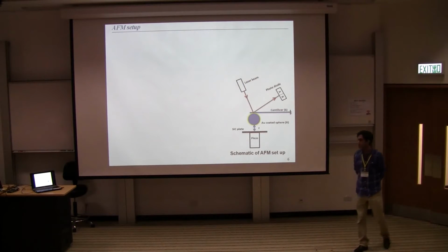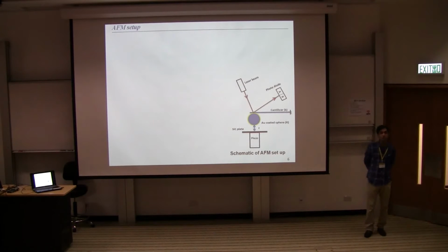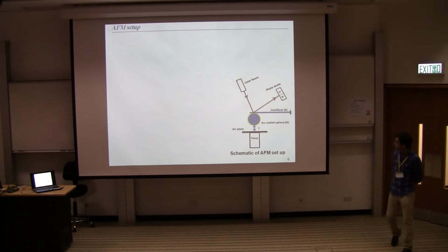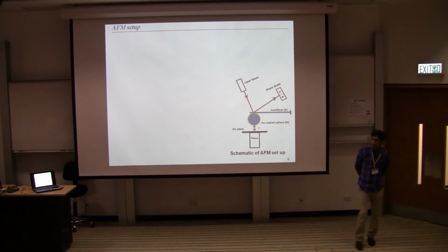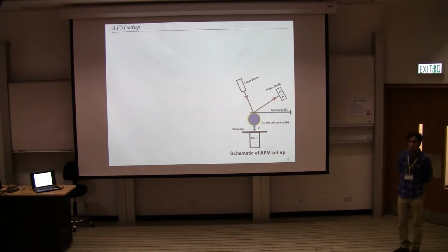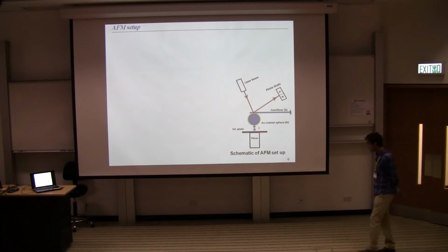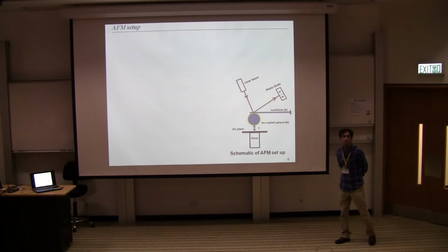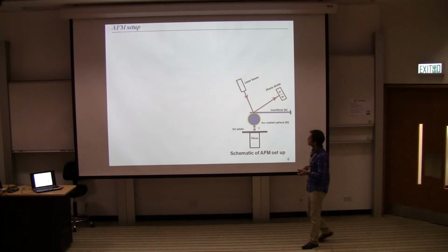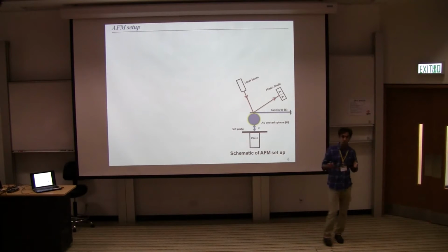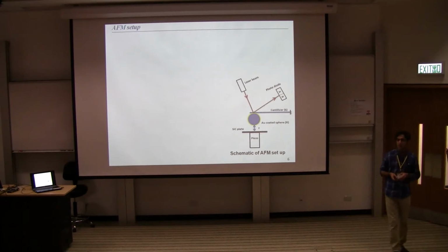So this is the schematic of the AFM we use for force measurement. We have a gold-coated sphere interacting with a silicon carbide plate. But since both samples are hydrophilic, vapor condensation and formation of a capillary meniscus lead to surface jump to contact and prevent the cantilever from retraction, despite using a ramp size of several micrometers.